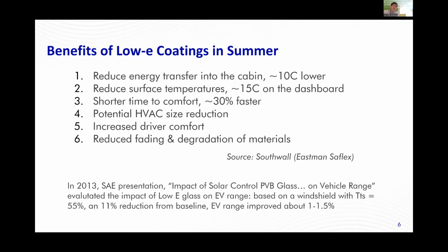I'll also point out there was a very good study done about 10 years ago on the impact of these types of low-E glass systems on vehicle range. They looked at gas, hybrid, and electric vehicles. I'm going to focus on the results from electric vehicles, using a windshield that had a TTS of 55%, which was down from the baseline study of 62% for the green glass windshield that was in it. Range improved about 1 to 1.5%, but at that time the TTS value might have been at best standard. Today the TTS values are much lower. I think it'd be worth revisiting that study to update it, because I think the EV range improvement would be quite more than what they saw, given the improvements in the TTS.